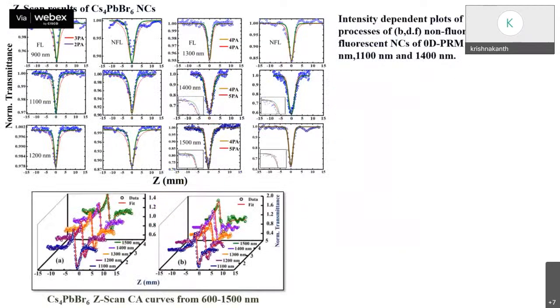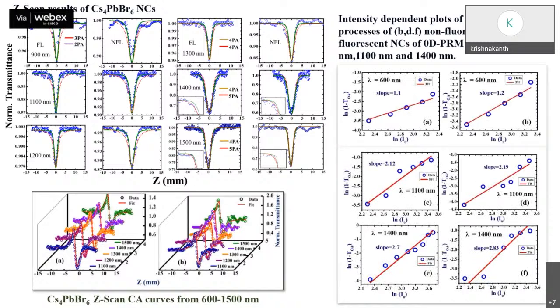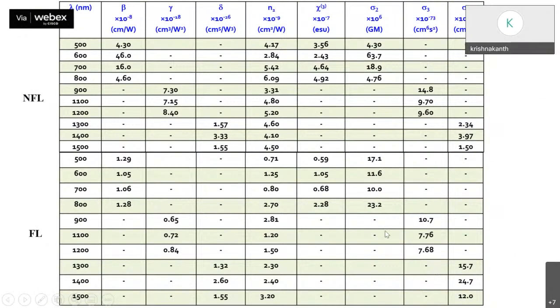These are all Z-scan parameters, ranging from the visible to the NIR range, meaning 500 to 1500 nanometer broadband studies we have performed. These slopes confirm that it is 2-photon, 3-photon and 4-photon absorption. These are the total NLO quantities for 2-photon, 3-photon and 4-photon absorption, which have higher values, mainly from the quantum confinement effect.